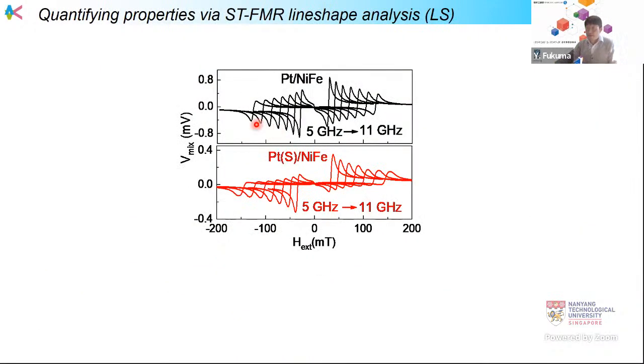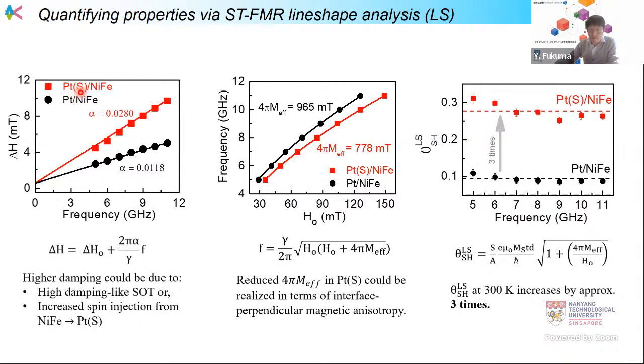This is the result of the spin torque FMR spectrum for the platinum layer and the sulfur-implanted platinum sample, as a function of the frequency. By analyzing these spectra, we can estimate the damping factor and the effective magnetization of the permalloy. What we can see here is that in the case of sulfur-implanted platinum, we can see an increase of the damping due to a larger spin pumping effect. At the same time, we can see a decrease of the effective magnetization for the sulfur-implanted sample.